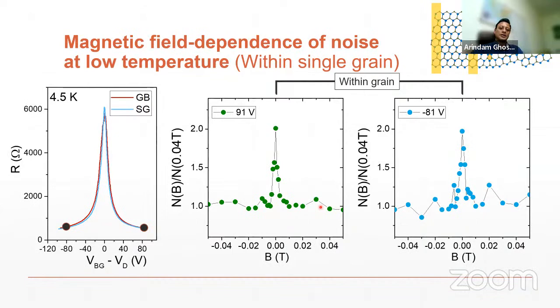And whether you are here or here or here, it doesn't matter. Noise comes down by a factor of 2 always, which means that within the single grain region, the time reversal symmetry is maintained at all temperatures and at all gate voltages.